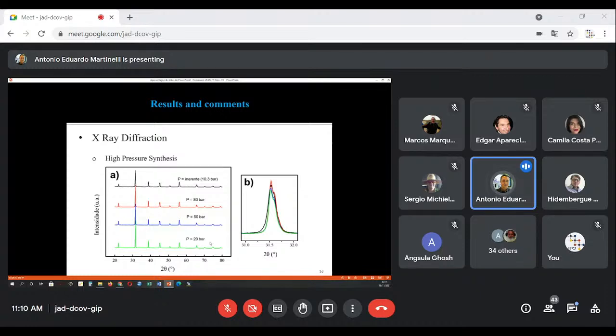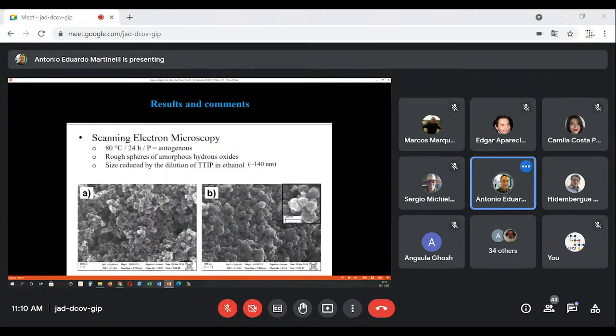Here, we maintain the temperature at 180, but now we increase the pressure to see the effect of pressure. Actually, here on the top, we have the autogenous pressure of 10.3 bar, 20 bar, 50 bar, and 80 bar. And we see that, as we expected, the increasing pressure does not change the composition, does not change the phase formation, just the characteristics of the particles.